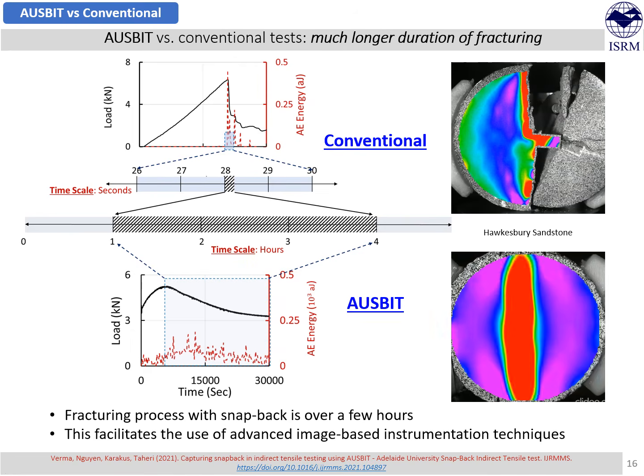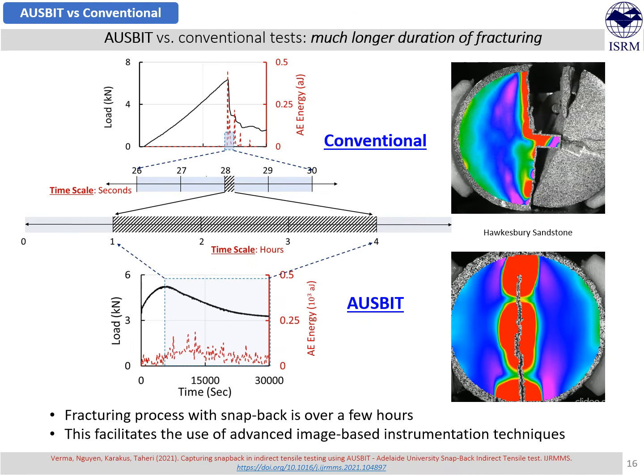You can see from these two disk specimen cracking videos, in the conventional approach, the disk was cracking in a fraction of a second. Now the same cracking process has been prolonged to several hours in AUSBIT experimentation. The acoustic emission energy response indicates that the whole cracking process is a valid cracking process. It's not the machine's mechanical unloading. You can see there has been a consistent release of acoustic energy indicating continuous damage of the disk under the AUSBIT experimentation post-peak response.